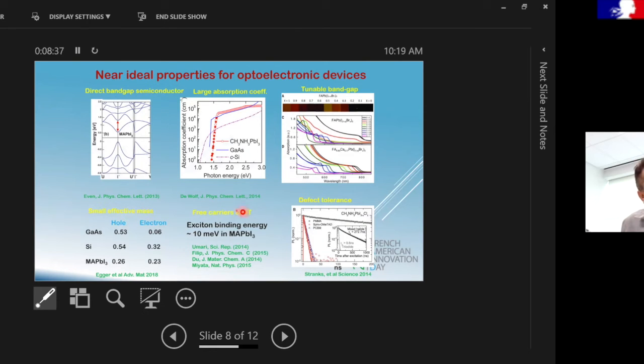In addition to this, they are very good for transport. For example, the charges that are created when the sun shines on it are quite light and they can move around very easily in the lattice. But more importantly, a very important trait in this material, which is different from other semiconductors, is that these are defect tolerant. What I mean by that is that when you create this material, of course, it has a lot of defects, but these defects don't tend to disrupt your charge transport, which helps you in making an efficient device. And so this really helps in getting an efficient device, despite the fact that there are these defects. And so these carriers live in the material for a very, very long time. And so this is really an important property, I think, that researchers all across the world are trying to understand.